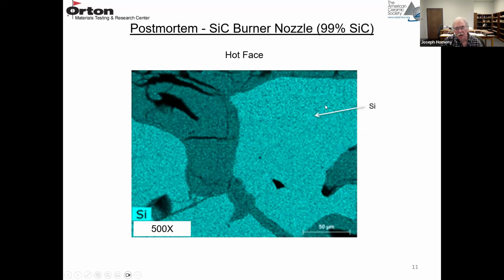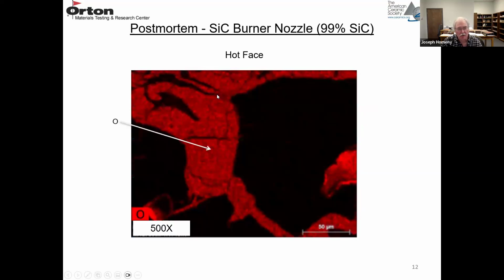So the turquoise again is the silicon carbide, the brightest part, and then the part that's less bright is the oxidized portion. And one thing to note, this oxidized portion is highly microcracked, so that deteriorates the structure. And again, the red here is the part containing oxygen, which has been oxidized.